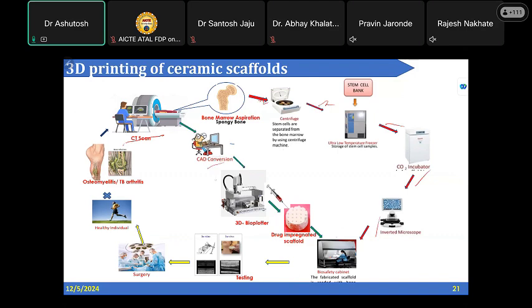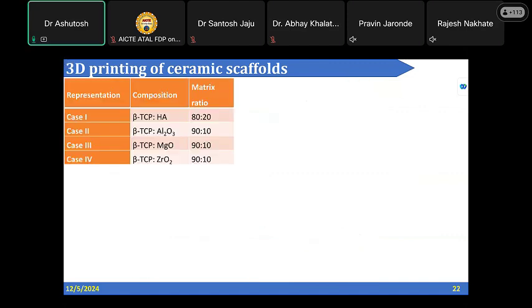Once we are converting this into CAD data, we are using the 3D bioplotter, which I used at VNIT, this one. And we are printing a 3D printed scaffold where we are encapsulating the drug as shown in this part. Similarly, we require a bone marrow aspiration. From spongy bone, we can get the bone marrow, and then we can isolate the required cell line. We can keep the cell line stored in stem cell banking, incubate it, see the morphology through an inverted microscope, and bring it to the biosafety cabinet. Now the drug impregnated scaffolds are seeded with the required quantity of cell line, which goes to in vitro testing, in vivo testing, followed by animal trials and human trials, and we will get a healthy individual. So this is basically the cycle for tuning natural bone requirement.